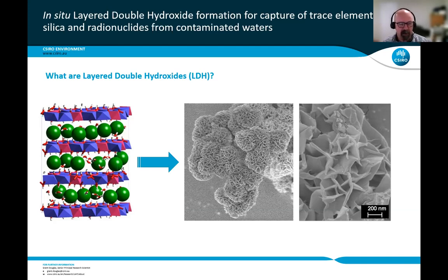So what does that look like in practice? Well, here's actually some in situ layered double hydroxides we produced from a uranium mine groundwater, which I'll talk about a little bit later. But I've termed these as botryoids, almost look like bunches of grapes. And then when you actually have a look at those in higher magnification, you've got the scale bar there of 200 nanometers, you can actually see the layered double hydroxides face to face and face to edge and so forth. If you look at the little one, the actual edge that you can see edge on there, just to the left of the 200 nanometer scale bar, that's around about, say, 20 nanometers thick.